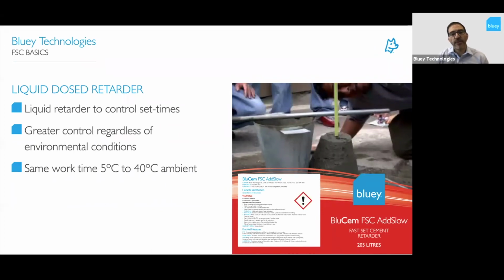So every 10 degree of temperature change in the ambient temperature would either double or halve your set times. So if you were hoping for a 30-minute set time and suddenly you had temperatures which were 10 degrees hotter than what you were expecting, you would only have 15 minutes of work time. And that's a pretty big hit to take in terms of the amount of work time. And then on the other hand, it could go the other way as well, where you don't develop the strength in time.